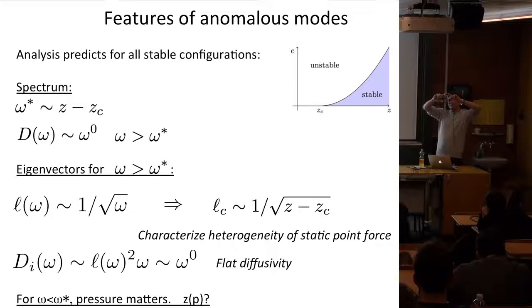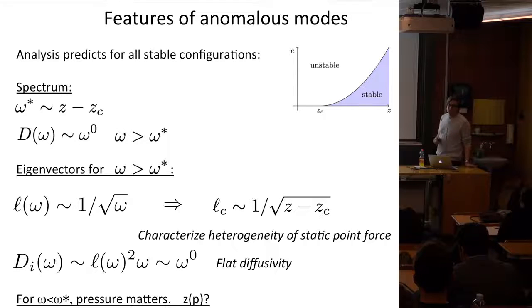So remember, at jamming, this was completely flat, the density of vibrational modes. Now you can look at different frequencies and look at those eigenvectors, and you can define a correlation length for them by looking, for example, at displacement. And what the theory predicts is that this length scale goes like 1 over the square root of frequency. That's from effective medium, and I don't have a very simple argument to say that. But once you have that, you can intuitively understand several aspects of the problem. One is, since you have a characteristic frequency and a length scale for those modes at any frequency, you get a characteristic length scale. And that's the one that enters in those heterogeneities in the response to a point force.